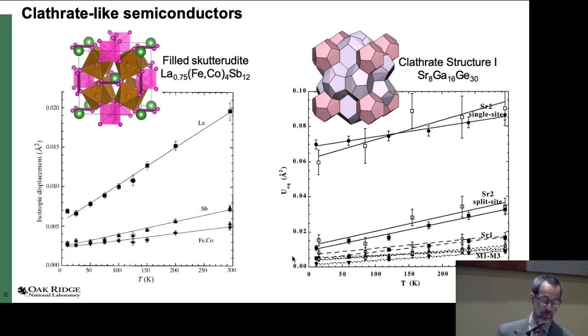We've used these simple notions to look at thermoelectric materials to gain insight in how one can tailor their lattice thermal conductivity, which is important for optimizing thermoelectric efficiency. Here, the clathrate-type thermoelectric materials such as the filled skutterudites and the structure type 1 clathrate show anomalous temperature dependence of the displacement parameters of the atoms that are in the large cage.